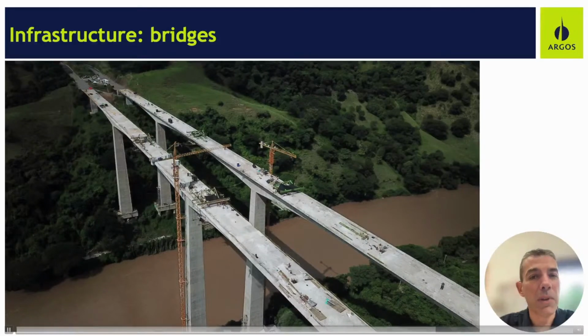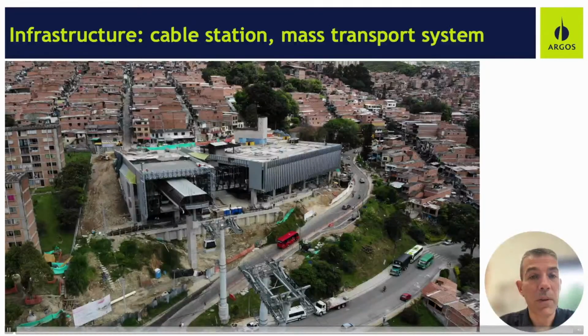Here you see our limestone calcined clay cement being used at a viaduct over the Cauca River in Colombia. You can see it's a very impressive bridge, very high, quite long as well, with very demanding structural performances. So this product is used in every kind of application that's going out of the Rio Claro plant. We have also used this cement in the mass transportation solutions in Medellin. So this is a cable station in the middle of the city, as you can see, where we used this limestone calcined clay cement to build all the pillars and in general all the stations and everything that was needed for this project.